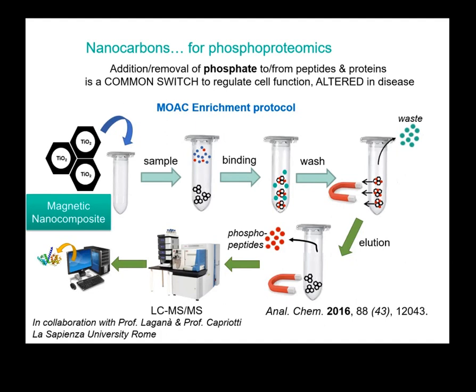And one of the interactions can be, for instance, as mentioned, between phosphates of phosphopeptides and metal oxides, in particular titania, which has shown a very promising performance in this regard. And then you can do analysis, for instance, through tandem LC mass spec equipment.